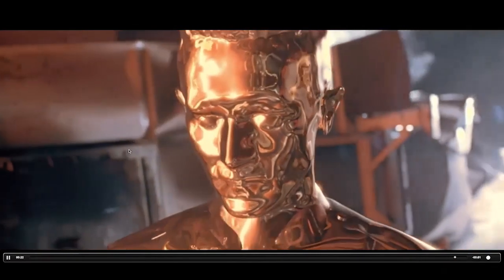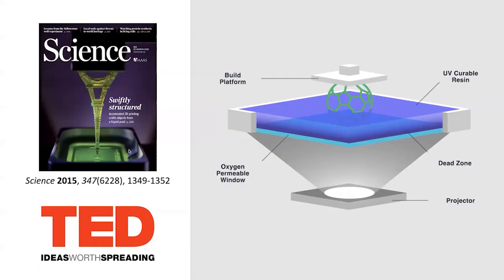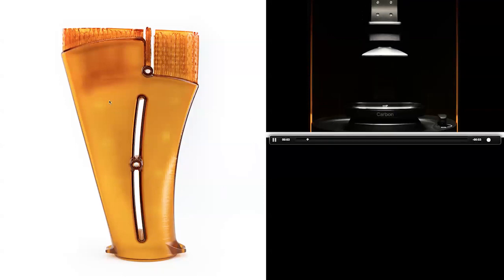And in that regard, we developed a process where we would use a light-based process, using 385 nanometer LED light, a digital light projection system, through a very special window that was not only optically transparent, but would be permeable to oxygen. And so what will happen is we lower a platform, and that very first layer would bond to the platform, but not to the window, because oxygen is an inhibitor of free radical polymerization. And so what happens is you lower this platform into this liquid, and we're going to make this object on the left.